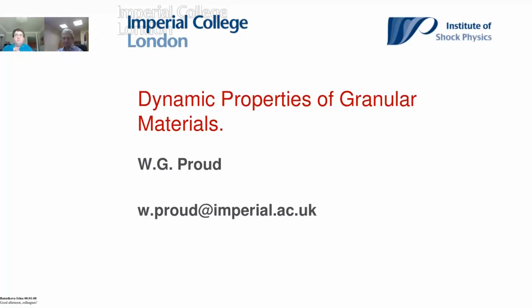I've seen 5%, which is one extreme, and 40%, which is fairly normal. A lot of our studies in these materials are round about 40% porosity, because with the best will in the world, our particles tend to have a somewhat spherical or ellipsoidal shape, and that means that we will ultimately end up with a certain porous fraction. But if we can change that, if we can control that, and with 3D printing and additive manufacture, we can produce these polydispersed systems with a range of voids in them. I think that provides a way to access these rather strange behaviors. Anyway, that would be a thing that I think deserves better attention.